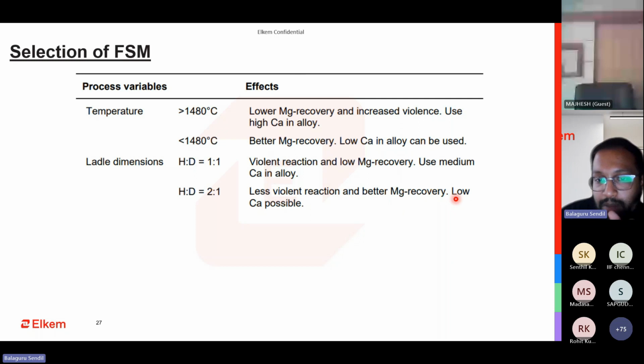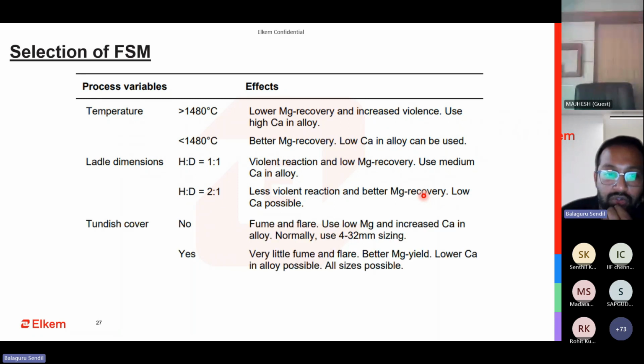So you don't need to use so much calcium. The calcium will help to calm the reaction. But at the same time, if you are having a very nice ladle with the 2:1 H by D ratio, then you don't need to go for 2.5% or 3% calcium. Calcium will help to calm the reaction. But unfortunately, if you have more calcium, then it will create more slag also. So for the tundish cover, if you don't have one, it is always advisable to go for a tundish cover.